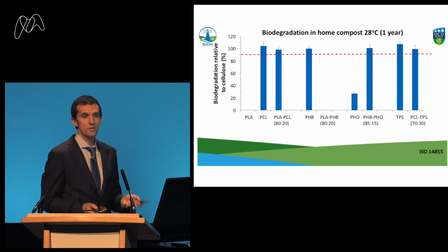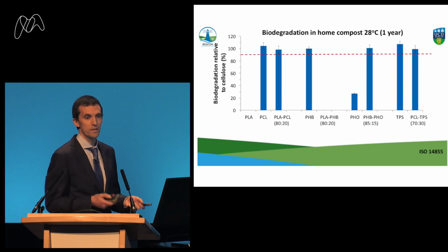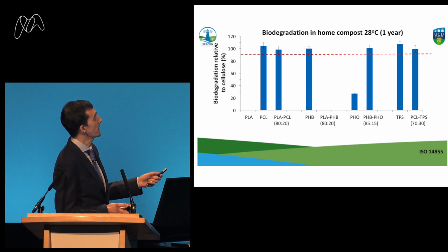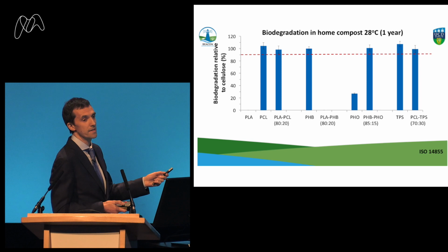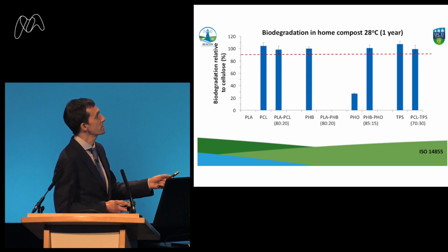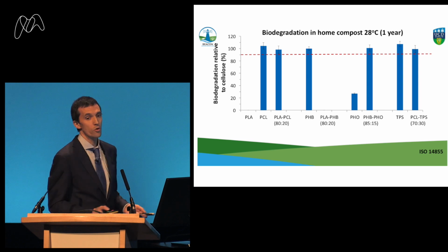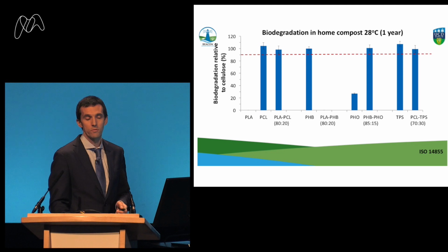So we started to look at these blends and see what could happen. We started to blend polymers. PLA, like I said, is not biodegradable, or not home compostable. PCL is. When we add 20% PCL into PLA, suddenly PLA becomes home compostable. We were surprised by this. Our partners were surprised by this. We repeated this so many times, and it always happens.